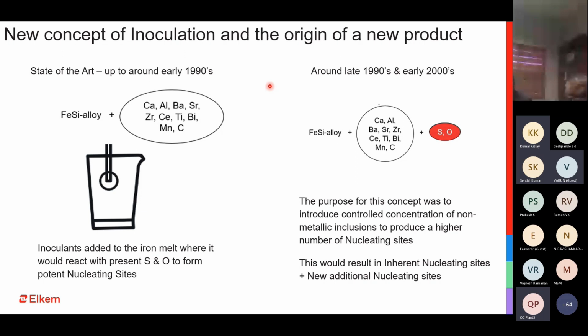So sulfur and oxygen coated inoculants came into existence about 20 years back, and since then they have been the go-to inoculants for many foundries who have been struggling with an inferior base metal. When I say inferior base metal, what do I mean here? We know pig iron can be a very good promoter of nucleating potential inside a base metal, but we also know that pig iron can bring with it many elements which we do not want in our iron, for example titanium, phosphorus, sulfur, etc. So when ductile iron manufacturers do not add pig iron, they inherently reduce the nucleating potential, because even when the pig iron was bringing the bad elements, it was also bringing in the nucleation. So the compromise was that we had to control the negative elements, and that is why we had to control the pig iron, but then we lost out on the nucleation.